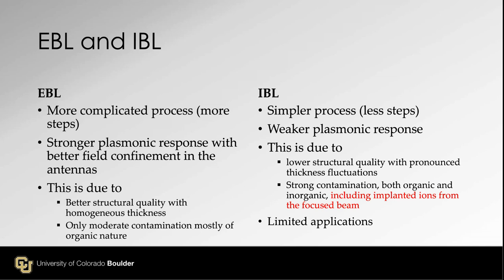However, the final device behaved much better with the EBL method. For this case, it's a stronger plasmonic response with a better field confinement in the antennas. That's what the research group liked a lot. This is due to the better structural quality with the homogeneous thickness of the metal structure and only moderate contamination, mostly of organic compound. That's EBL.